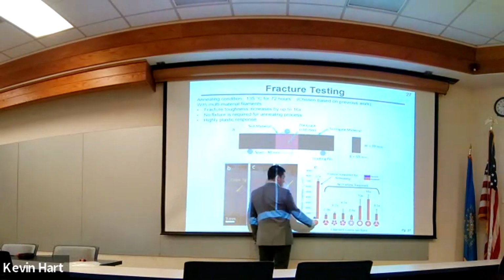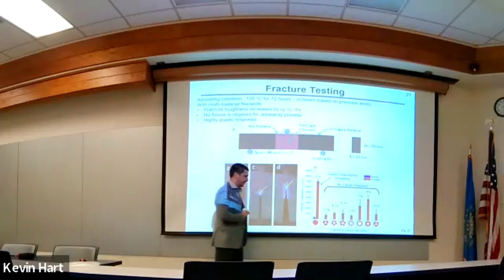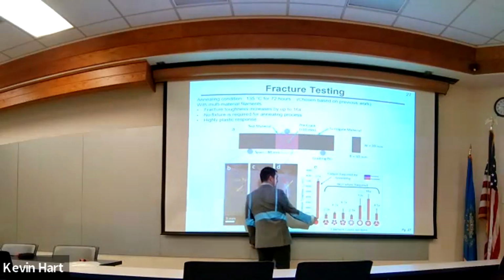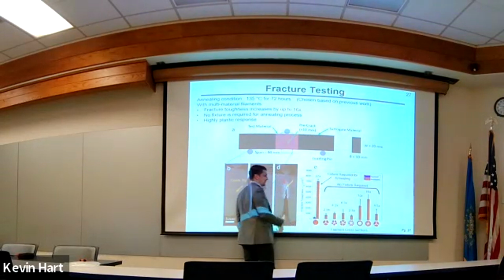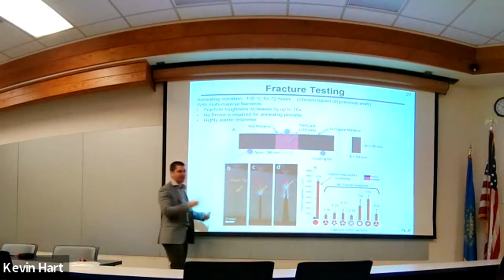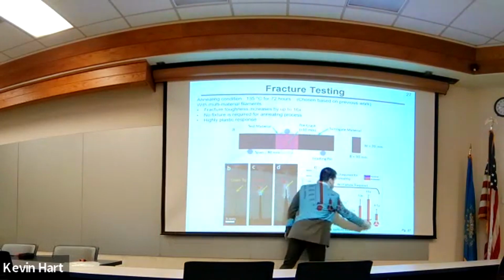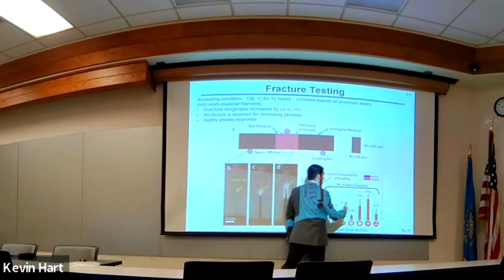So if I print a 3D printed sample with just ABS, and I do not anneal it, we know that the toughness is about 250 joules per meter squared. If I anneal it inside of a fixture, I get toughnesses of 7,000 joules per meter squared, like injection molded levels, right? Here are all the results that come from printing those fracture specimens, annealing them, and then testing these guys in fracture,